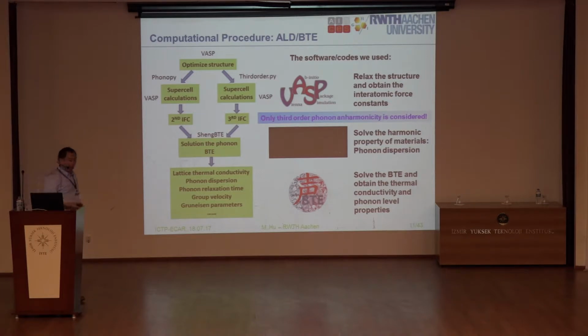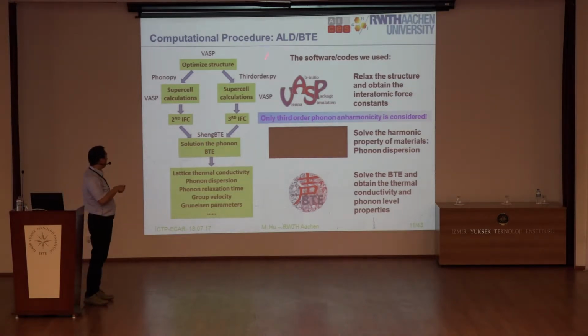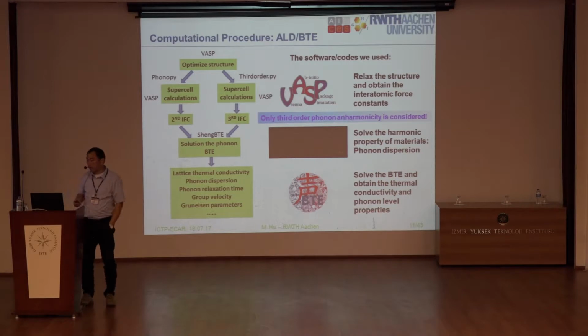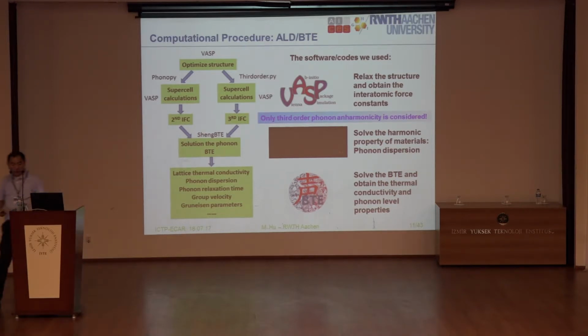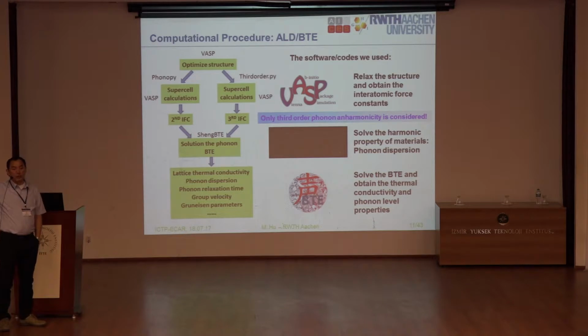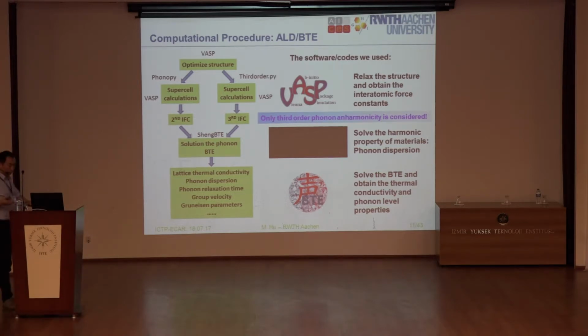So our computational procedure is based on first principles. We use anharmonic lattice dynamics coupled with the BTE calculation. I don't need to repeat the computing procedure here, and I just want to say that this approach is based on the assumption that we neglect higher-order phonon scattering. We just consider the third order, right? So the technique is mature, and we use it to screen materials.